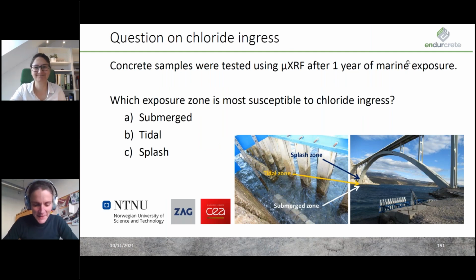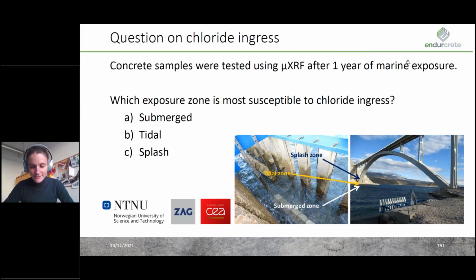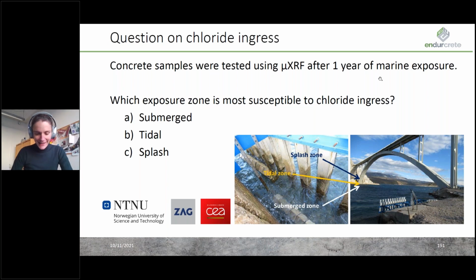Yes, thank you. So besides carbonation, we also looked into the chloride ingress in concrete, and the concretes developed in EnDurCrete. As most of you know, chlorides originate either from seawater or de-icing salts, and they can ingress into the concrete cover. When they reach a sufficiently high concentration in the vicinity of the reinforcement, they can cause corrosion. And it's actually this reinforcement corrosion which is considered one of the main degradation mechanisms for reinforced concrete exposed to seawater or de-icing salts.